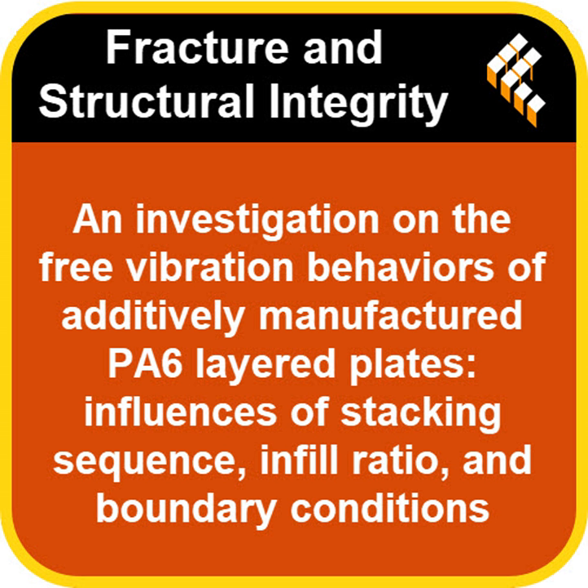Exactly. Putting stiff material on the outside is powerful for increasing frequencies, while putting dense material in the core can actually lower them, depending on the mode shape. So these results provide really valuable, actionable guidance for designers and engineers using FFF. Definitely. You now know you have specific parameters within the printing process itself, not just overall infill percentage, but how you layer it, and also external factors like mounting that you can leverage to tune the natural frequencies of your PA6 parts, to get better performance, better lifespan, better efficiency in real-world applications. It opens up exciting possibilities for optimizing printed parts beyond just their static strength or weight.